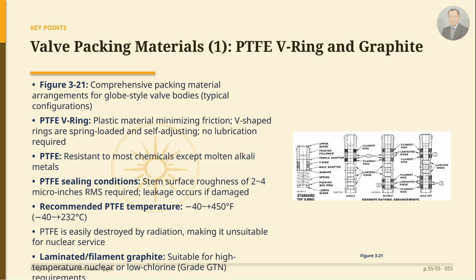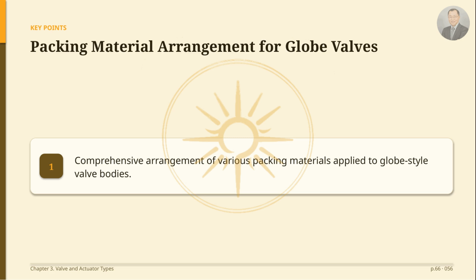However, for proper sealing, the stem surface must be extremely smooth, at a level of 2 to 4 microinches RMS, and leakage will occur if the stem or packing surface is damaged. The recommended operating temperature is from -40 to +450 degrees Fahrenheit, which is -40 to +232 degrees Celsius. One point of caution is that PTFE is not suitable for nuclear service because it is easily destroyed by radiation. For high-temperature nuclear environments or where low chloride content is required, laminated and filament graphite, specifically grade GTN, is appropriate. This is a comprehensive arrangement of various packing materials applied to globe-style valve bodies.